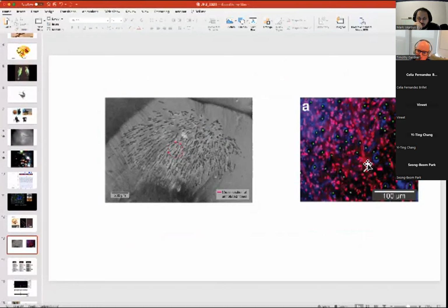This is at a depth of 3 millimeters below the surface. And then here's a really large bundle of fibers that we inserted, a few hundred of them, also at a depth of 3 millimeters below the surface. And so there's this really interesting surprise that these very, very flexible small fibers can be held together to be stiff enough during implant, but then they spread apart during insertion.